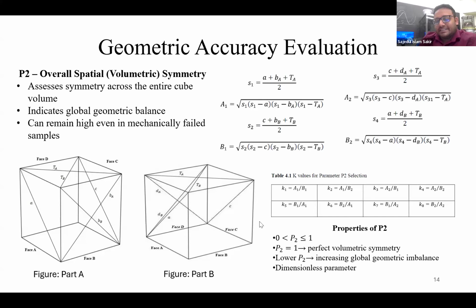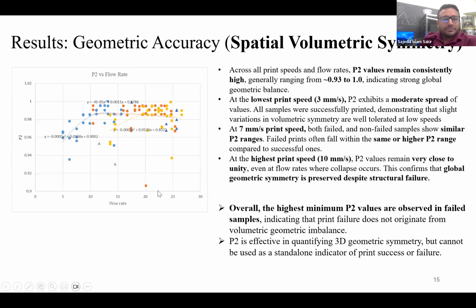So lower P2 is increasing global geometric imbalance, and it is also a dimensionless parameter. So I am showing the curve from the lab we have got. If you see here, we also have the P2 value starting from 0.93 to 1, indicating strong global geometrical balance. At the lowest speed, when it is 3 millimeters per second, all samples are successfully printed, demonstrating that the slight variations in volumetric symmetry are well tolerated at low speeds.